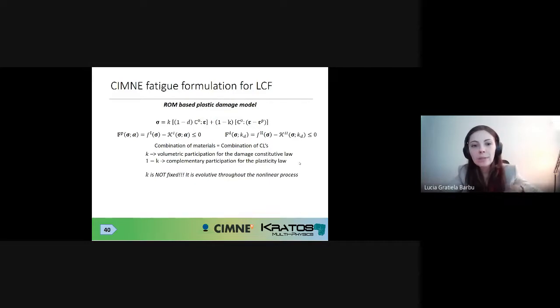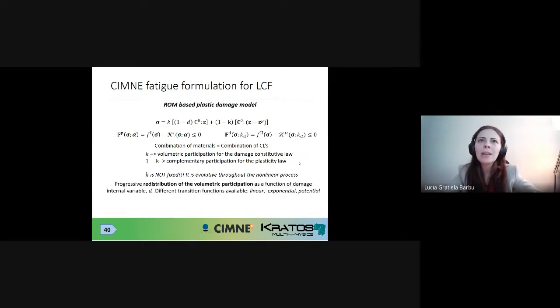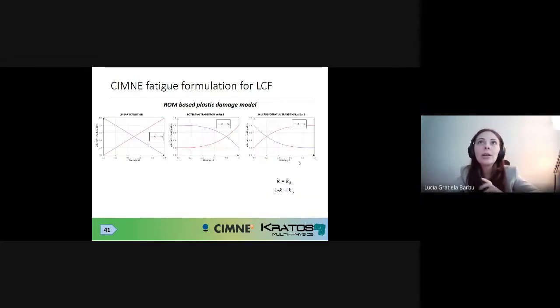So if you have a material which starts to exhibit plasticity at the beginning of the nonlinear processes, but later on migrates into a damage behavior, or a combination of these two, this model is perfectly capable of capturing this. This is a very, very important characteristic. So when we are dealing with progressive redistribution of the volumetric participation as a function of this damage internal variable, we have proposed different transition functions available: linear, exponential, and potential.